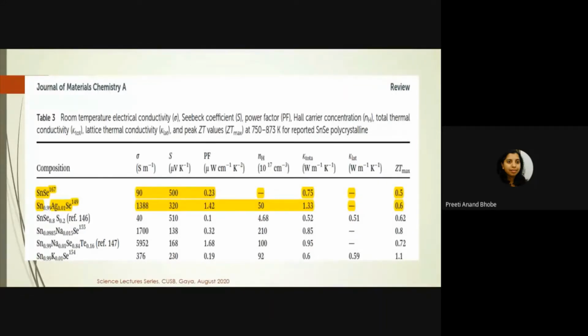The reason being that in a polycrystalline form, you are losing this layered structure, phonon propagation is much easier, and electrical conductivity gets affected, Seebeck coefficient gets affected. All these parameters are getting into the line of a major decrease in the ZT. So the scientists decided, and mind you, this was in 2014 itself, that if they want to increase this ZT, they should see which is the factor that is most getting affected here.